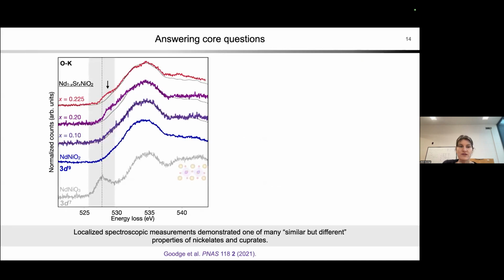Okay, so this is what we did in the case of these sort of first discovered superconductors. I'm not going to go too much into the details. I'm happy to talk with anybody who's maybe more interested. But what you see here are oxygen K-edge EELS spectra from those kind of local clean regions. So again, kind of pulling out just the crystalline regions that we're interested in. Of 4 different compounds, you see this sort of blue through red gradient.